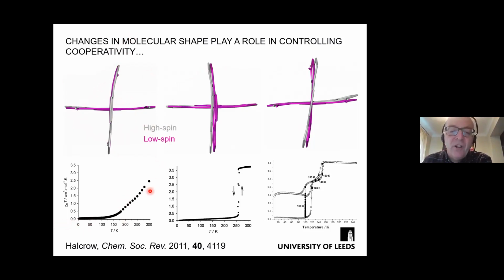And this spin transition is very gradual. Here we have a very anisotropic structure change. As well as changing its bond lengths, the molecule is changing its shape. And this leads to a much more cooperative and much more interesting spin transition with a sequence of phase changes and hysteresis and really everything you want. So if you're lucky, the complex within the crystal can explain the switching properties you see.